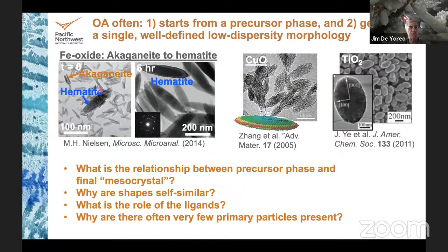So here, for example, you can see these beautiful spindles of hematite, Fe2O3, that form from akaganeite nanorods, which are the first particles to appear in this system. They organize themselves into these sort of football-shaped objects, but in the end, they're made of hematite. And so the question is, well, how does this work? How do you go from one phase that's organizing itself one way into another crystalline phase that's a perfect single crystal?